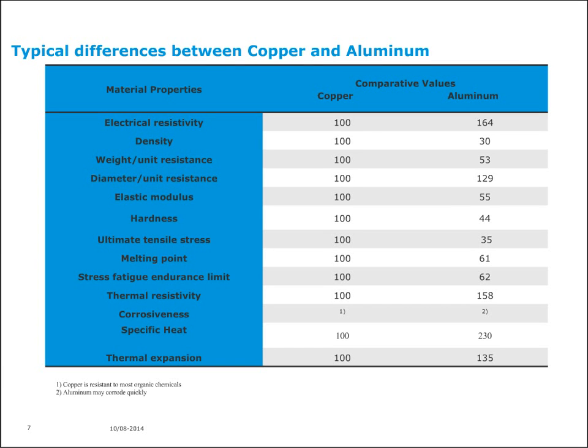The elastic modulus, when copper is given the value 100, for aluminum 55. Hardness, copper is 100, aluminum 44. The ultimate tensile stress, when you take 100 for copper, it's 35 for aluminum. The melting point, 100, then aluminum is 61. Stress, fatigue, endurance limits, 100, then aluminum is 62. Thermal resistivity, 100, 158.